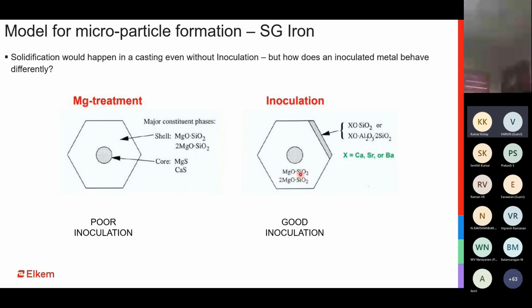Of course, you don't have the manganese sulfide in case of SG iron; you have more of magnesium sulfides and calcium sulfides, which form the core. And then you have the shell, which is made up of oxides of silicon and magnesium. So this is without inoculant. In this, you do not have a favorable site on which the graphite would precipitate, even though you have a core which is formed. But in this case, when you add an inoculant to it, which can be any of the inoculating elements, you are creating a site, you are creating a situation where the precipitation of graphite will be in a much more favorable manner, in a much more friendly manner.